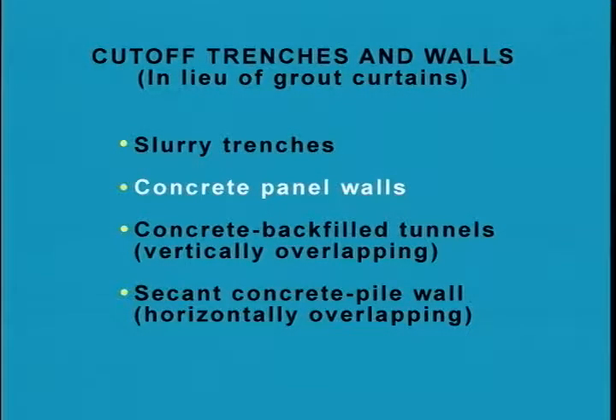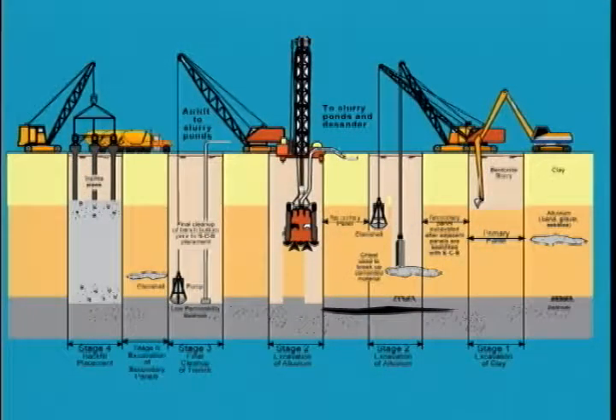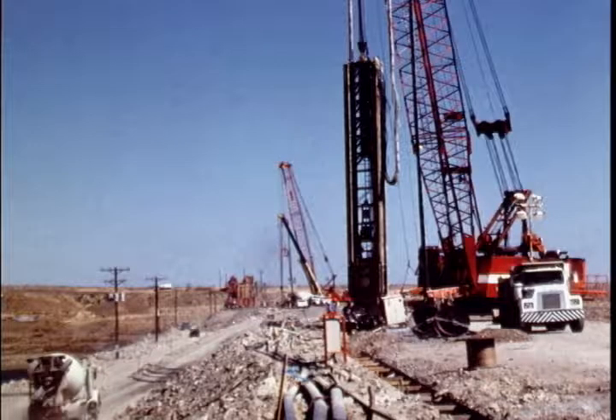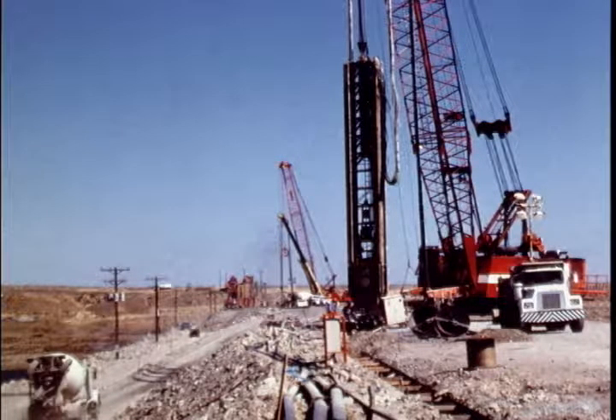Concrete panel walls of two-and-a-half to about five feet in thickness of cast-in-place concrete, trimmed into a vertical slot filled with bentonite slurry, are a popular type of cutoff below high embankment dams. The excavation is by an elongated clamshell working between surface concrete guide walls, with the wall excavated and backfilled in alternating panels. Depths of alluvium of up to 200 feet or so have been constructed by this procedure. Some designers prefer a very low-strength plastic concrete backfill to match the modulus of the alluvial foundation so that settlement of the wall and alluvium will be similar.